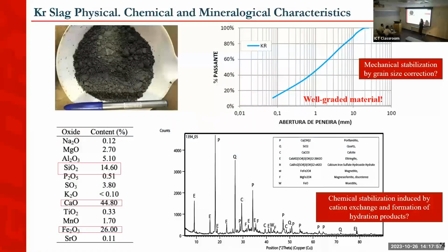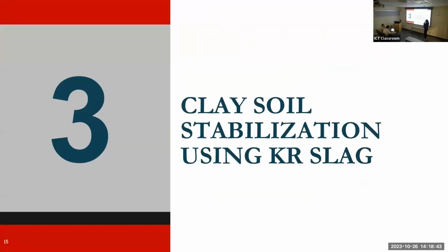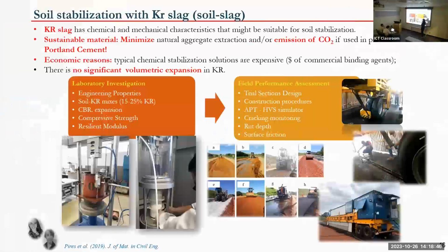But we also noticed from chemical analysis, X-ray fluorescence analysis, elemental composition, we saw the presence of silica, calcium, and iron, which are also common in cementitious materials such as Portland cement. And from X-ray diffractogram, we saw the presence of portlandite, quartz, calcite, and ettringite. So these gave us insight that this slag not only can be good for mechanical stabilization, but might give us some chemical stabilization because of those chemical components. So chemical stabilization induced by cation exchange and formation of hydration products, those were our initial thoughts. So we decided to move on to this study here about the use of clay soil stabilized with KR slag.